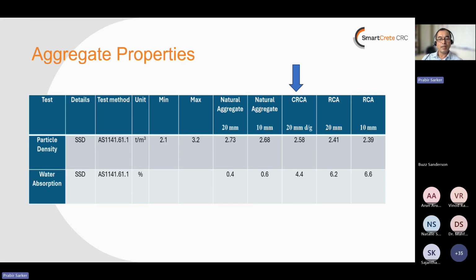Important properties are particle density and water absorption. For CRCA 20 millimeter, the particle density was found to be 2.58, as compared to around 2.7 for natural aggregate. The other important property is the water absorption. CRCA has a higher water absorption, about 4 to 5%. There is some comparison with C&D waste aggregates as well, where it was found to be up to 6 to 6.5%. Whereas for natural aggregate, it is very low, like 0.4%. So this is a well-known property that recycled concrete aggregate has a higher water absorption than natural aggregate.